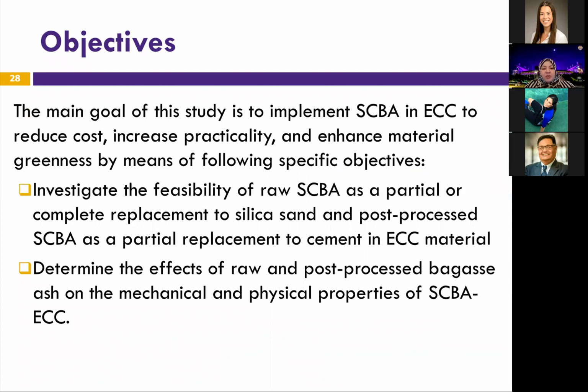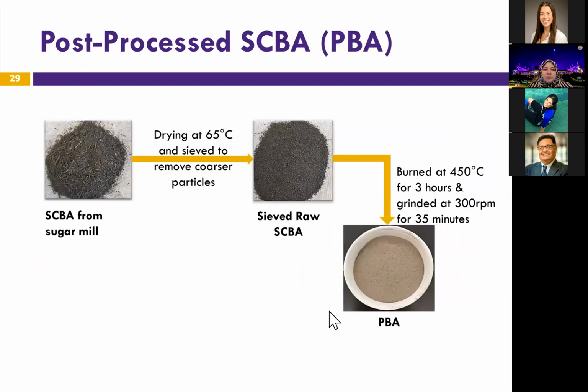So we said, can we process this bagasse ash so we can actually use it in ECC? And we were thinking of two usages for the ECC. One as a cement replacement to reduce the content of cement, and one as a sand replacement to eliminate the river sand or the microsilica sand. So we had to process the sugarcane bagasse ash first.